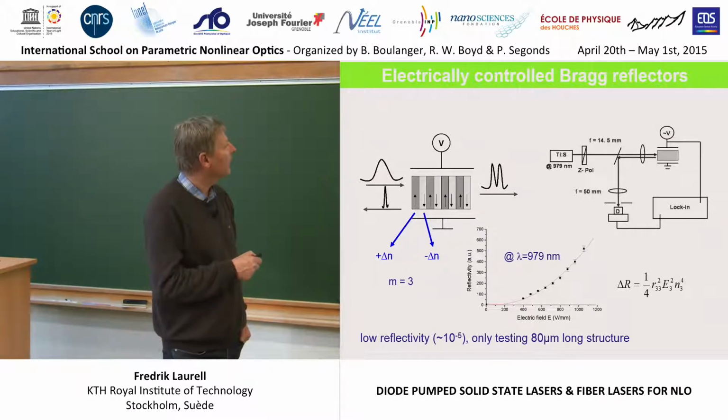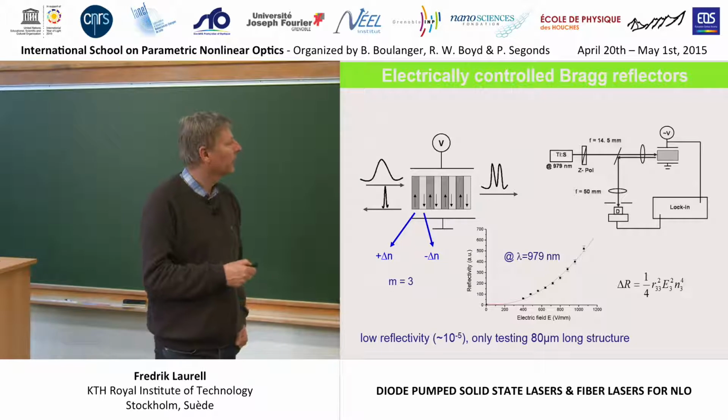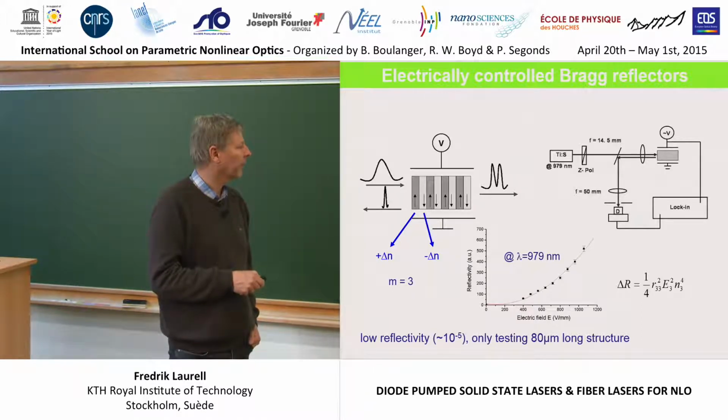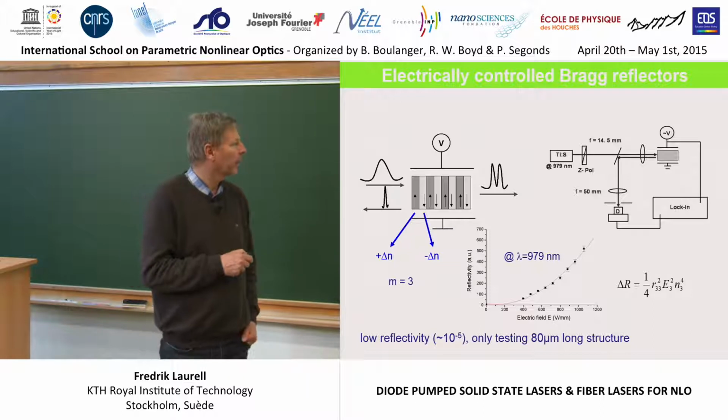So if we shine a broad spectrum onto this crystal, it will reflect certain wavelengths. And then we demonstrated that with a tunable laser, we can hit these Bragg peaks. Here it was still a higher order Bragg reflection for the Ti-sapphire laser. But at 1.5 microns, I think one can reach today with the technology available, maybe first order.